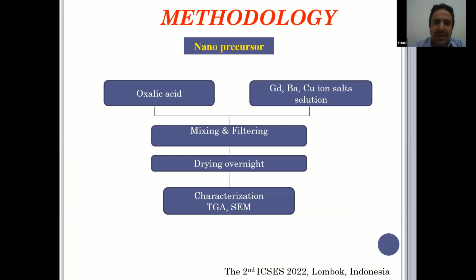In the methodology, we normally start by preparing the nano precursor, which is mixing oxalic acid with gadolinium, barium, and copper ion salts. Normally we use acetates, or we can use nitrates. We mix them in the right proportions. The ratios are normally 1 to 2 to 3 molar ratios with oxalic acid, forming a complex. This complex will be filtered and dried overnight, and then the dry powder will be tested by TGA and SEM.